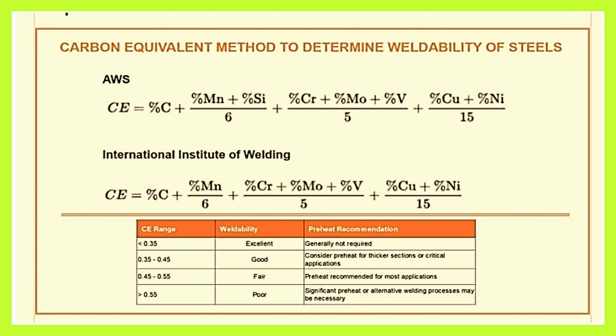I told you that with less than 0.35 carbon equivalent, it has excellent weldability, generally preheat not required. 0.35 to 0.45 is good weldability. Consider preheat for thicker sections or welded parts to be used for critical applications. 0.45 to 0.55 is fair. Preheat recommended for most applications. Greater than 0.55 carbon equivalent, we have poor weldability. Significant preheat and alternative welding processes may be necessary.